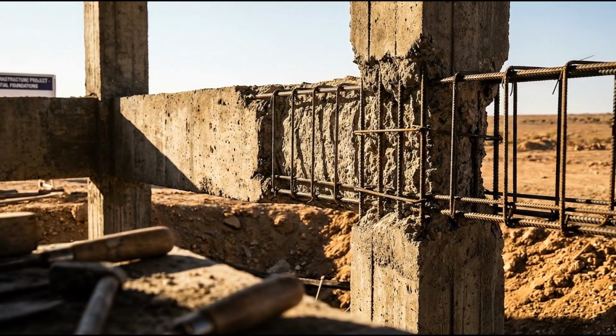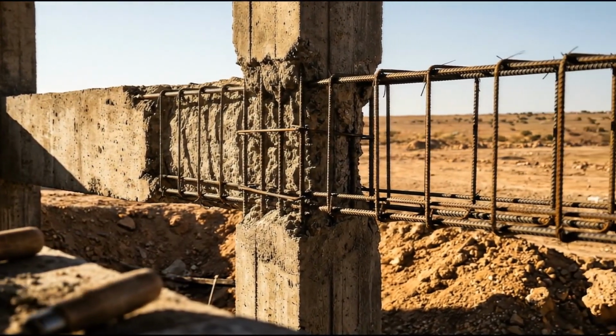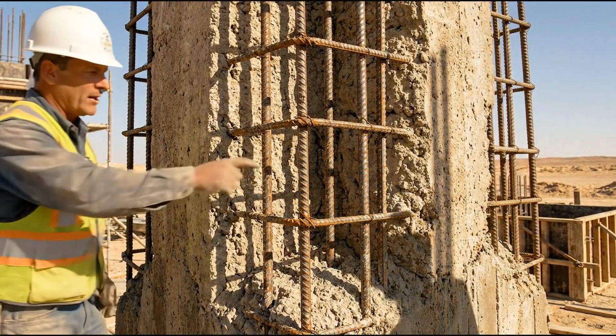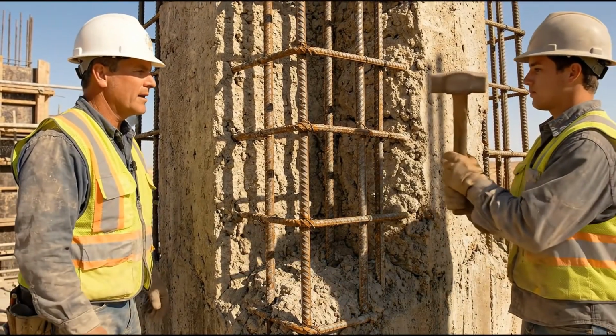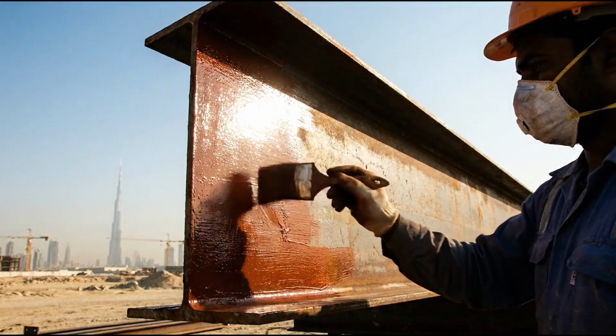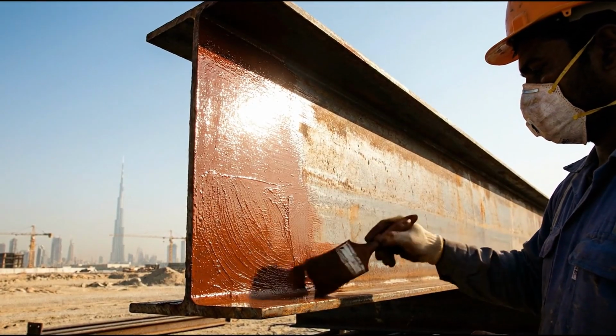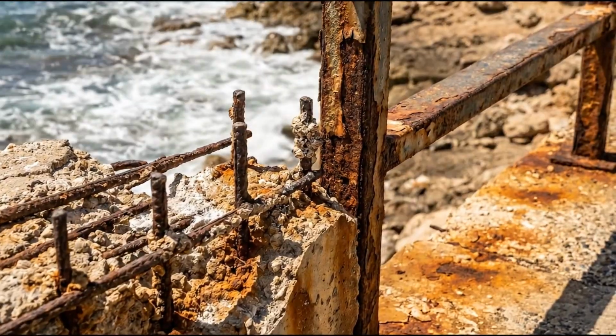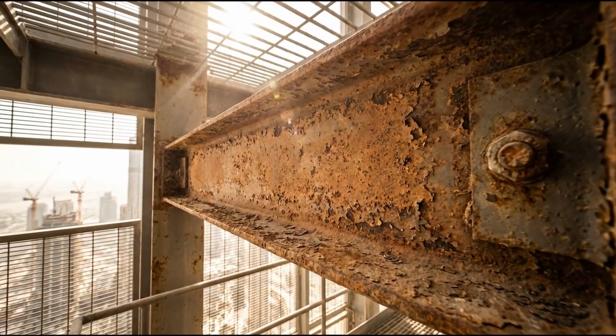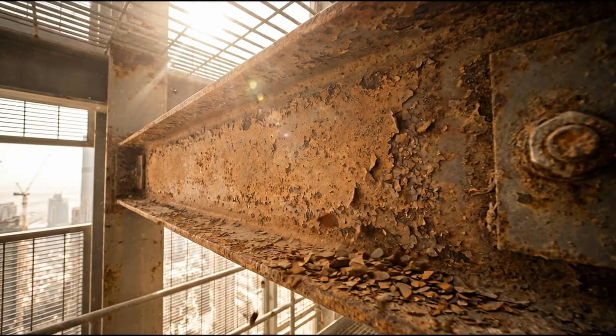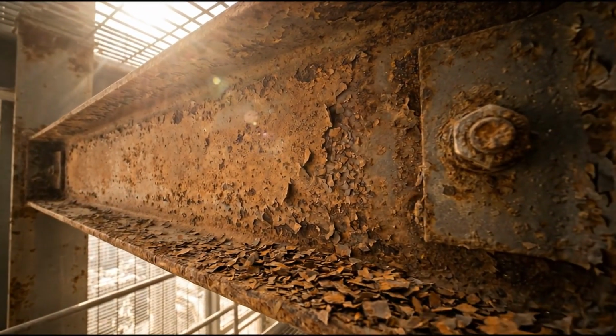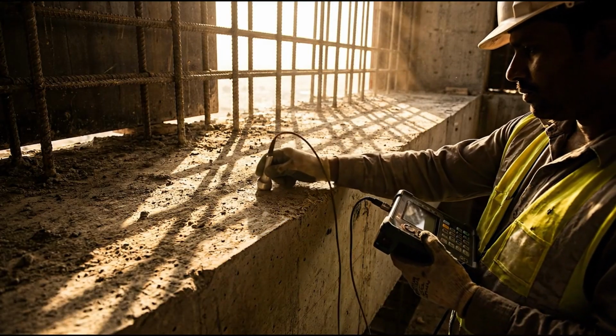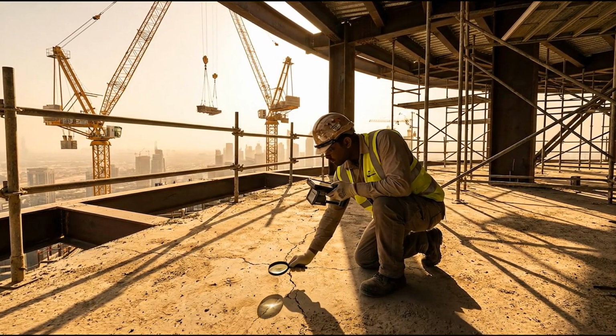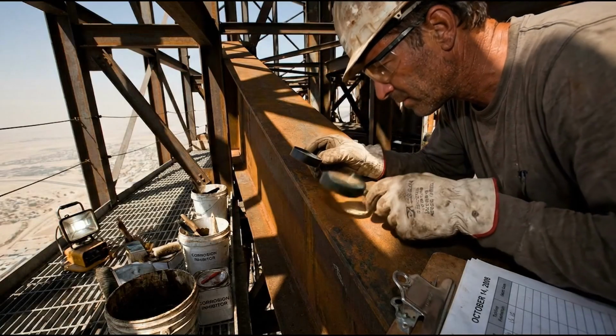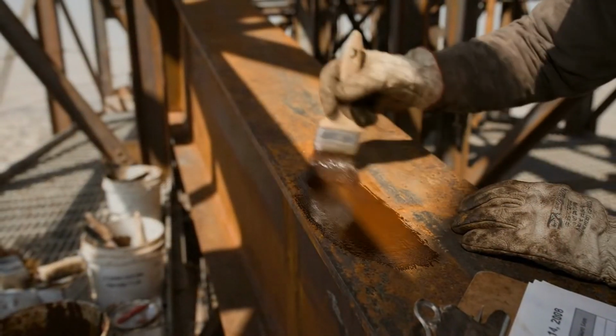In standard construction, reinforced concrete is considered durable. Steel rebar embedded inside a concrete column is protected by the alkaline chemistry of the concrete itself, which forms a passive layer around the steel and prevents rust. But introduce enough chlorides into that environment, and the passive layer breaks down. The steel begins to corrode. Corroding steel expands, cracking the concrete from the inside, and once concrete cracks, more water enters, accelerating the process. Left unchecked, this cycle can compromise a structure in decades rather than centuries.